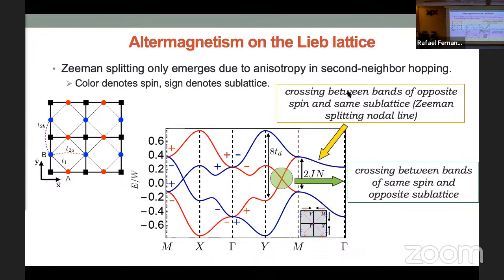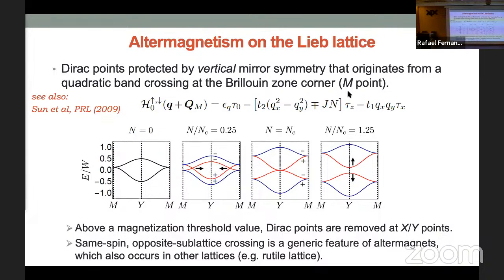Okay. And it turns out that these nodes here are protected, and you can actually understand them as arising from, if you start with zero magnetization and you start increasing the magnetization, they start from a quadratic band touching. So you start with quadratic band touching, you disturb it, you get these two Dirac crossings, and I keep increasing my magnetization. The only way to get rid of them is when they meet and are removed at the Y point. So you see, we usually focus on this regime here, where the magnetization is large enough and I have an isolated band. But a lot of the times, especially when this is not very large, which I can control with temperature, I'm going to get these additional Dirac points. Okay? And you can show that this is quite a generic property. There's no way of avoiding it.